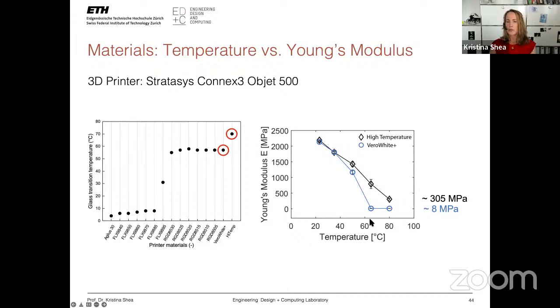So he's looking at these two materials, the high temp material and Vero White, which is a rigid material. And you see here on the right-hand side that the Young's modulus, when you heat it, changes non-uniformly between those two materials. So at this temperature, about 65 degrees, you get a big spread between the Young's modulus. What he used is actually the 80 degree temperature, because it was just more reliable. These temperatures aren't exact when you're heating the materials. And there, the difference in the Young's modulus is 305 megapascals and 8 megapascals.